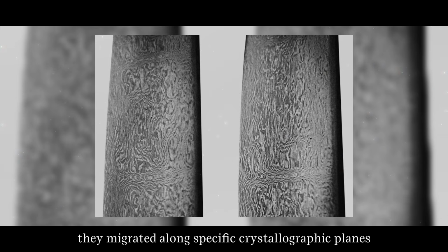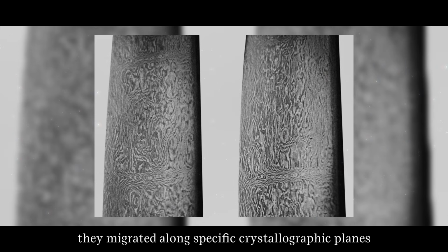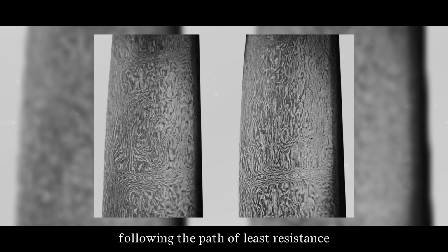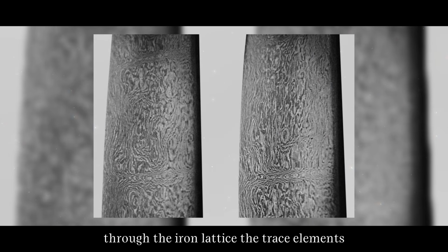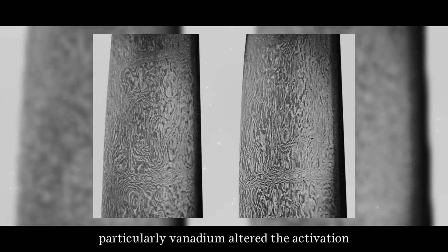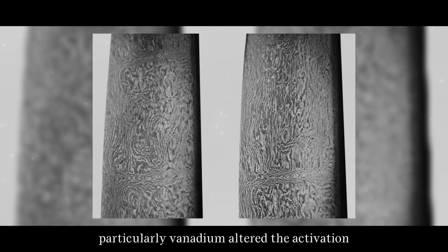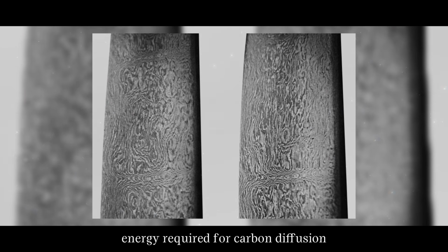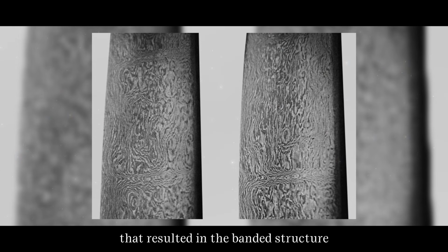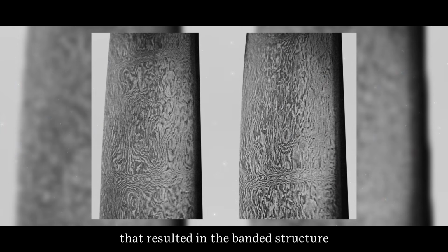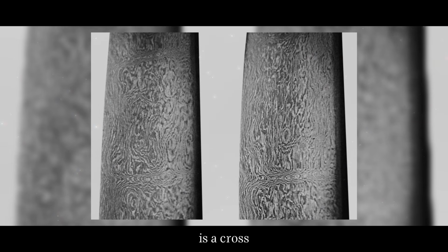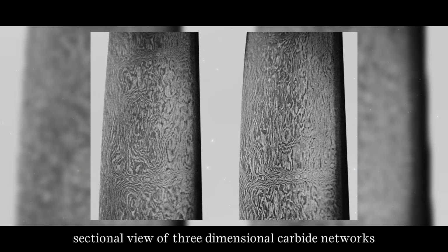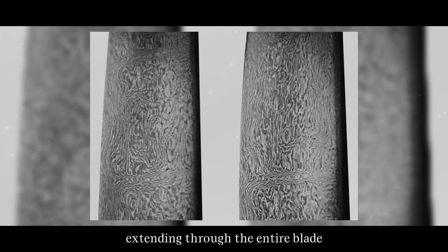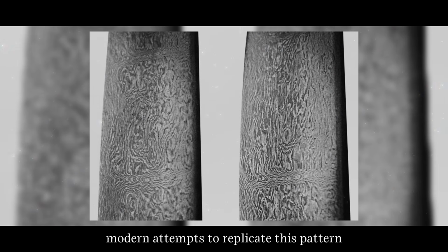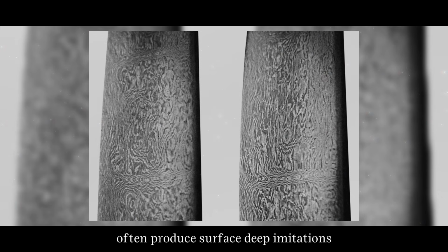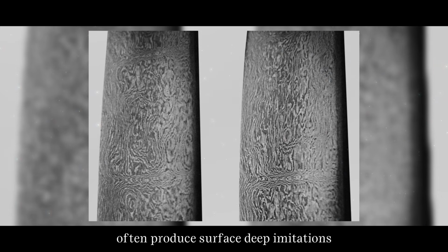That fractal boundary exists because the carbon atoms didn't diffuse uniformly during solidification. They migrated along specific crystallographic planes, following the path of least resistance through the iron lattice. The trace elements, particularly vanadium, altered the activation energy required for carbon diffusion, creating preferred pathways that resulted in the banded structure. The pattern you see on the surface is a cross-sectional view of three-dimensional carbide networks extending through the entire blade.